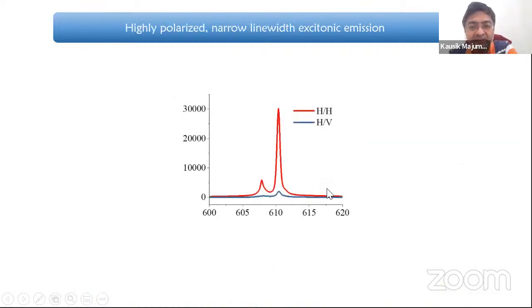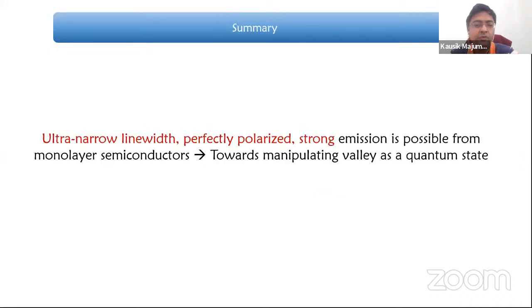This is also a highly polarized system. The polarization is maintained very nicely. This is not exactly 100%, but we got something like 90% polarization from the stack. So that's all I have. I wanted to conclude by saying that this ultra narrow line width and perfect polarization is really possible from these monolayer semiconductors, which earlier we thought was not possible. This is a good step towards manipulating valley as a quantum state.